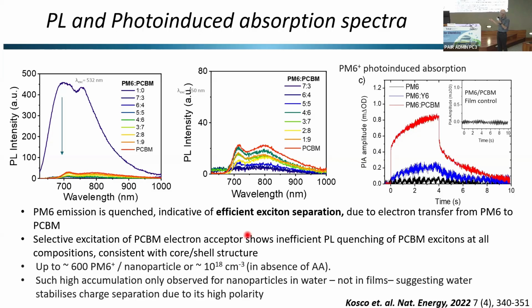Another thing is that when we look at the intensity of the PIA spectrum, we can calculate we've got around 600 charges per nanoparticle, so 10^18 per centimeter cubed. This is much, much higher than the maximum you'll ever see in a solar cell. And that's quite an interesting thing. And so why is this? Well, we think it's because these nanoparticles are in water, and this water on the surface, with its high dielectric constant, screens and stabilizes these charges so they can persist for a long time, and they're really highly dense. So this is, I think, quite an interesting observation and quite unusual.